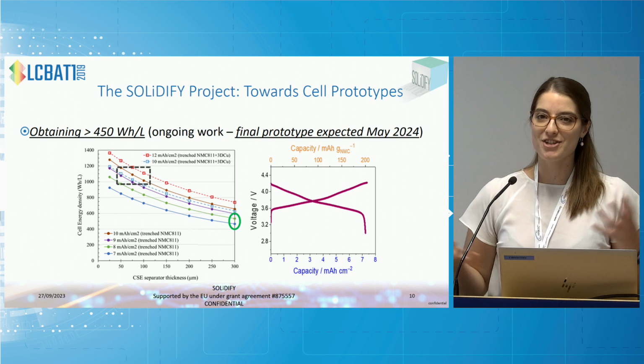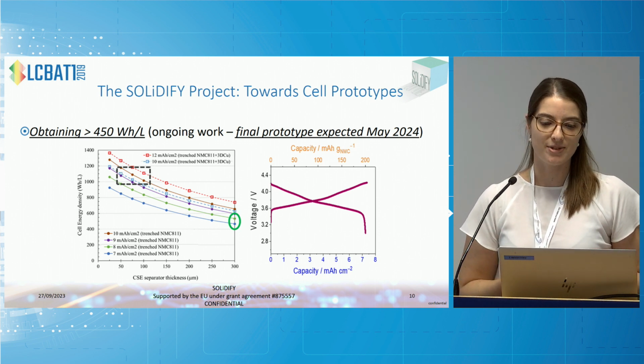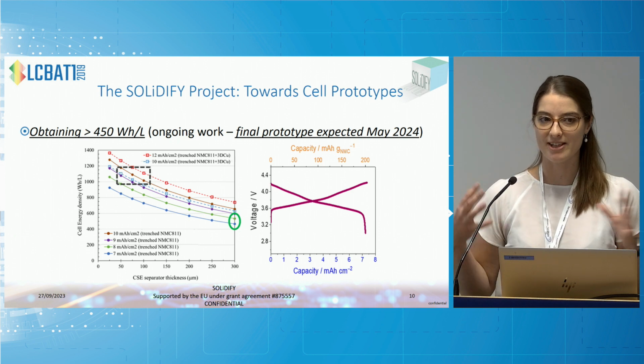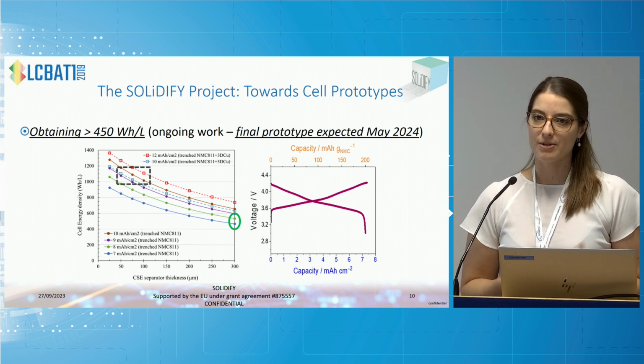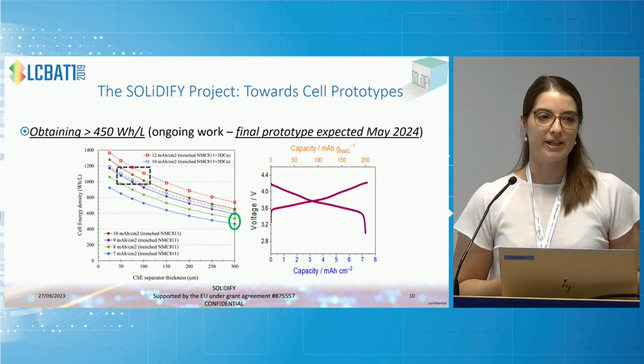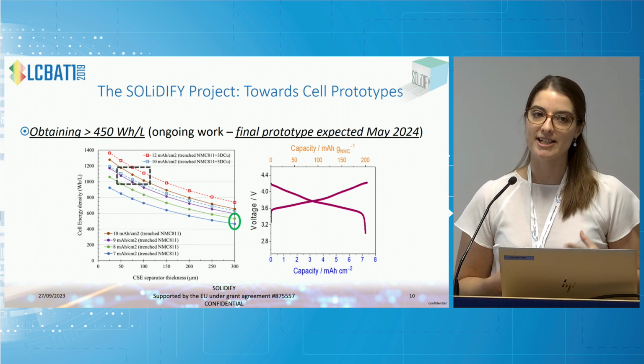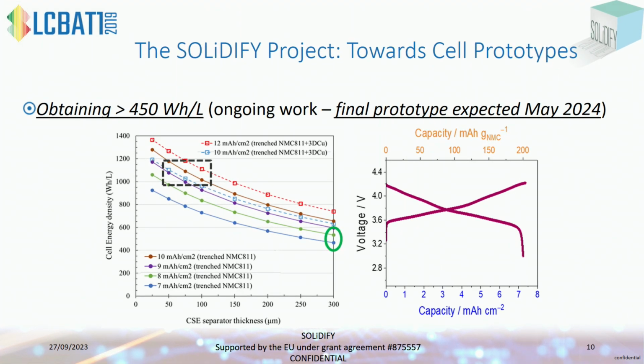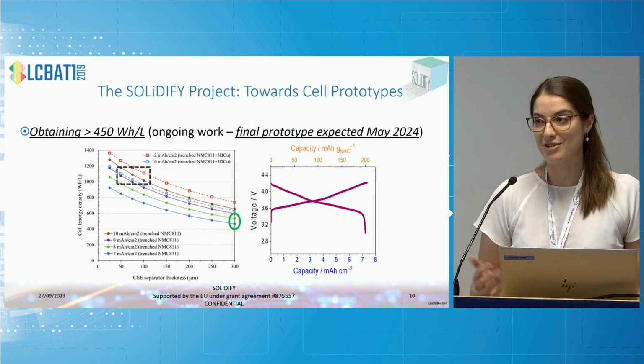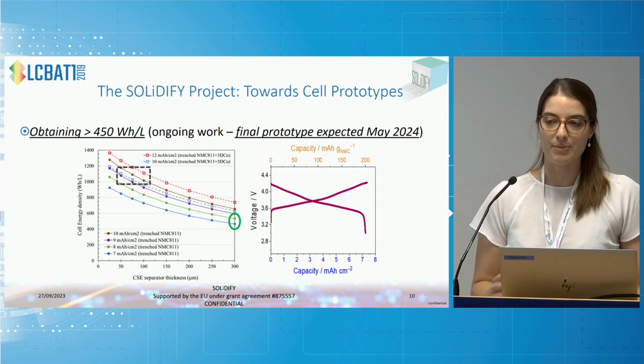Finally, it's nice to show where we're actually at with the cells themselves. So this is really ongoing work. It's not the end result, let's say, but we thought it would be nice to show what we could expect from a final prototype. And we have challenges which will be highlighted in later topical sessions. At the moment, our first prototypes for SOLIDIFY, we've been able to obtain more than 450 watt-hours per litre. You'll see here on where we expect to go with the thickness of separation. We're at quite a high separator thickness, but this is very much preliminary. We have issues, of course, challenges with solid electrolytes, like many others here, with their mechanical stability.